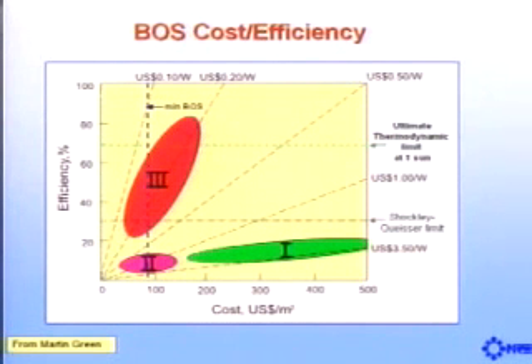Now, in order for solar photon conversion to produce both fuel and electricity economically at 1 to 2 cents per kilowatt hour to have the major impact, this would require a conversion system at about 40 cents per peak watt, based on these numbers. Now, again, this comes from Martin Green, and it shows the three regimes of photovoltaic conversion. And these dashed lines represent a given dollar per peak watt. So any combination of areal cost, dollars per square meter, and efficiency, just multiply this by a kilowatt per square meter, and if you're on that line, that'll give you this given cost per peak watt.